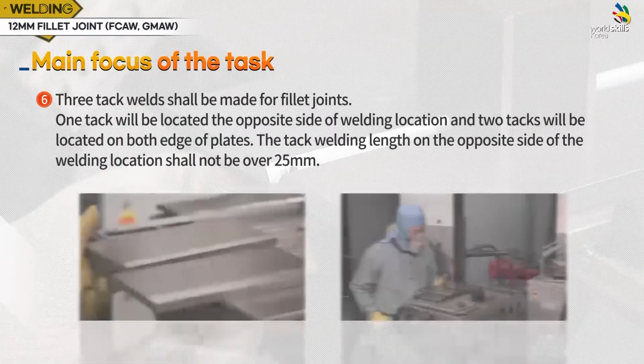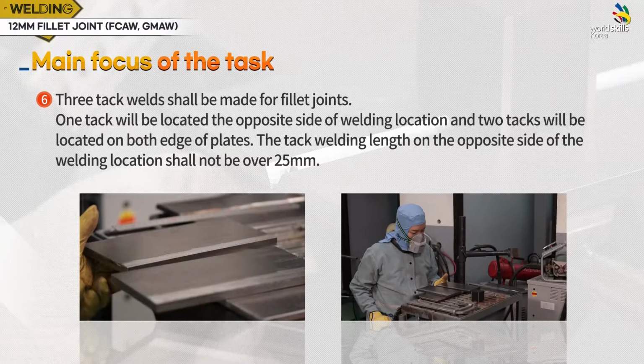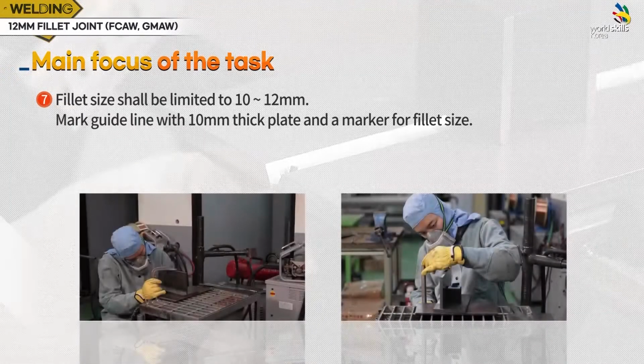3 tack welds shall be made for fillet joints. 1 tack will be located on the opposite side of welding location, and 2 tacks will be located on both edges of plates. The tack welding length on the opposite side of the welding location shall not be over 25 millimeters. Fillet size shall be limited to 10 to 12 millimeters. Mark guide line with 10 millimeter thick plate and a marker for fillet size.